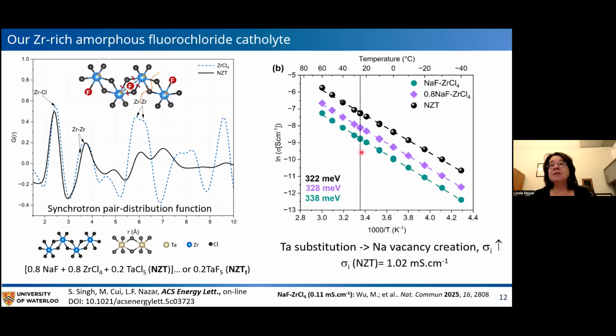And so if you compare NZT, which is the zirconium with the same sodium concentration but with the tantalum, versus just this sodium fluoride, zirconium chloride, which was reported last year, you can see that the conductivity increases significantly from the 0.11 millisiemens of the so-called parent material to around 1 millisiemens for this tantalum-doped material, and of course the activation energy drops accordingly.